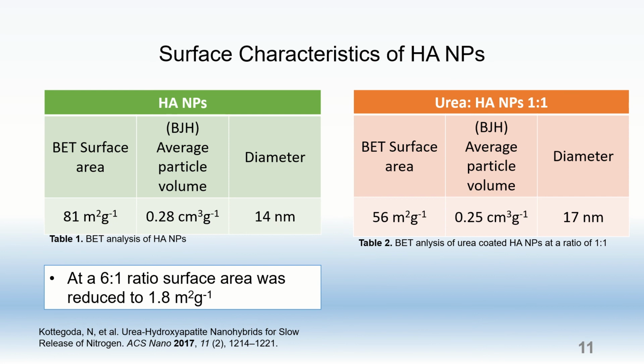Next, in order to understand the surface characteristics of the hydroxyapatite nanoparticles once they were coated with urea, BET analysis was carried out. Table 1 here shows the results of pure hydroxyapatite. It had a surface area of 81 meters squared per gram, and according to the BJH method had an average particle volume of 0.28 centimeters cubed per gram, with an average particle diameter of 14 nanometers. Comparing this with the urea-coated hydroxyapatite nanoparticles in a 1-to-1 ratio shown here in Table 2,